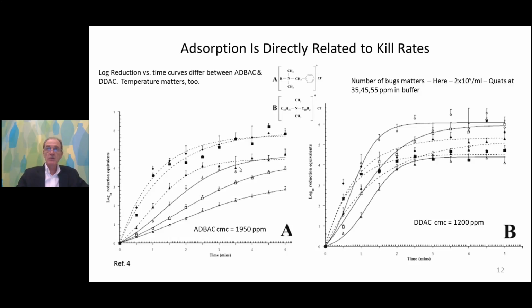These curves also point out one other thing that I want to ask if someone's noticed. After about 3 or 4 or 5 minutes, we reach a plateau in the log R. What does that mean? Who can catch what that actually is implying?